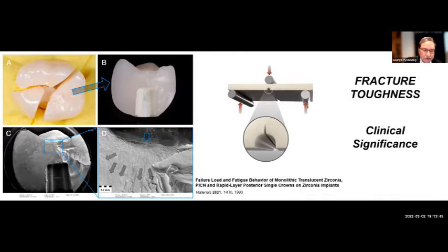The second property, which is becoming more and more popular from ceramic engineers because it really measures the resistance to crack propagation. And crack propagation is what induces failure clinically for this matter. So if we have a contact area, basically a functional area that's hitting, we have too high of occlusion, excursive forces, whatever, it may initiate a crack and propagate. This micro crack can then expand with the hydrolysis of the materials, creating a fracture of the material.